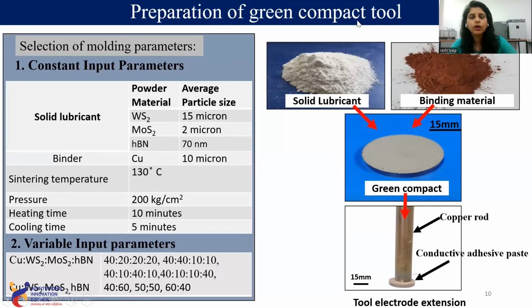This is how we have prepared the green compact tool. These are some constant input parameters that we are using: solid lubricant and powder material are constant. We are using WS2, MoS2, hBN, and copper powder. This is the average powder particle size, and this is the sintering temperature applied in the hot mounting press. Basically, these are the hot mounting press parameters in which we are making the green compact tool. The pressure is 200 kg per square centimeter, heating time 10 minutes, cooling time 5 minutes.